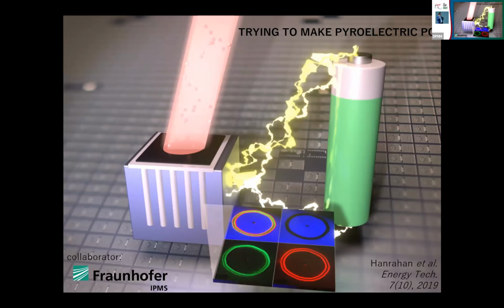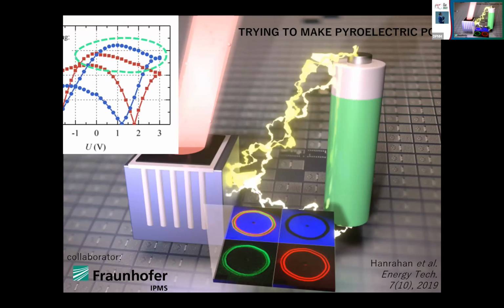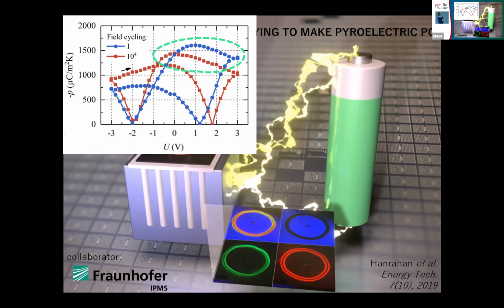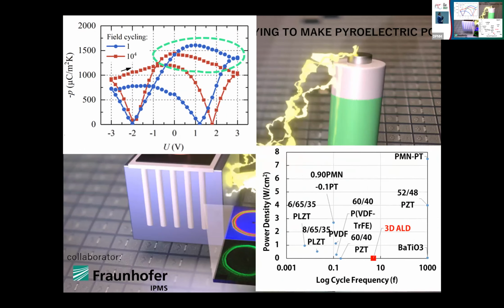You may know some of my previous work. I was all about pyroelectric energy conversion. And I had gotten a sample from our collaborators at Fraunhofer that was a very high surface area Hafnia ferroelectric that we were using for pyroelectric energy conversion. And the apparent, keep in mind that this is normalized by the surface area, not the total area, the apparent pyroelectric coefficient was monstrous. I mean, for a planar PZT, it's more like 200 or 300. And yet, if you benchmark our 3D ALD Hafnia against what else has been in literature, somehow this plot didn't make the paper. It was way down towards the bottom.